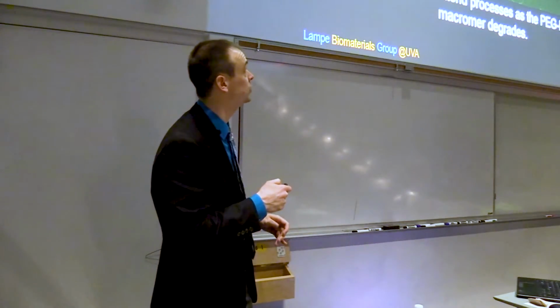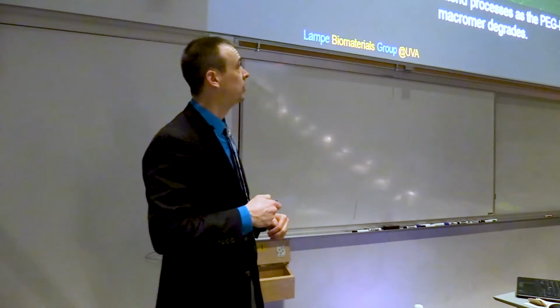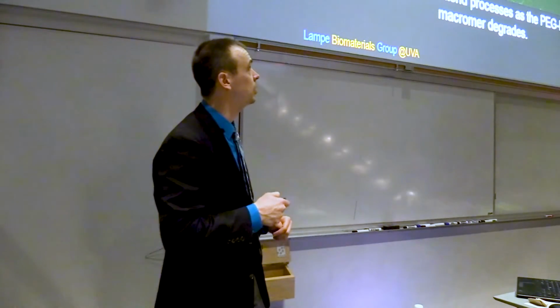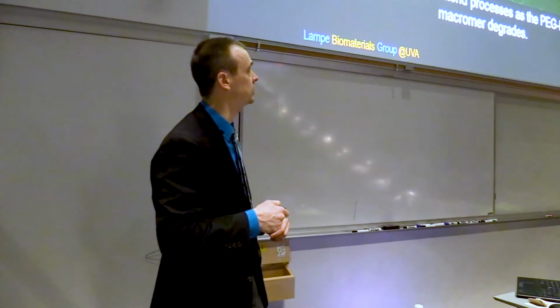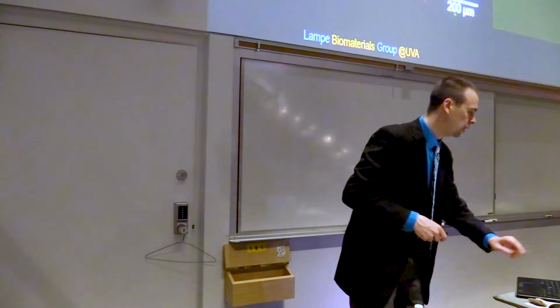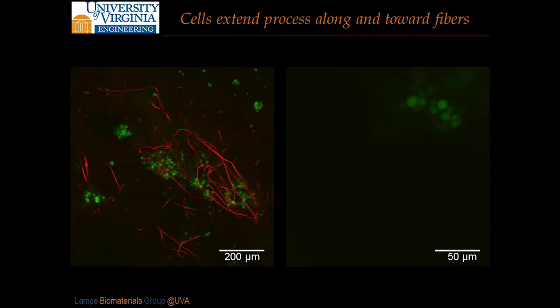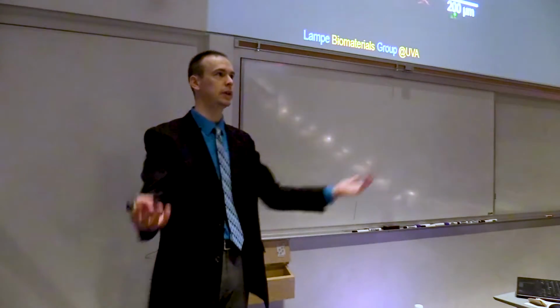If you make a stiffer hydrogel, higher weight percent, the cells are still stuck, right? But if you wait long enough, they will start to extend processes. But you see in this case, lots of tight, rounded up cell clusters. Right? If we now say, well, what if we give them something to pattern on, right? And so in here now you're seeing in red are fibers that we've just encapsulated into our hydrogel.